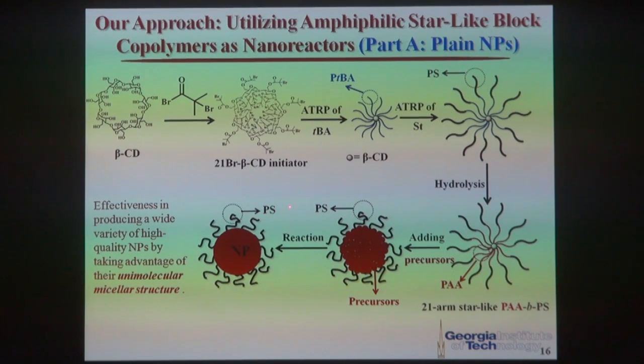So now because of the covalent connection between polystyrene and polyacrylic acid, right? They are covalently connected. So we are talking about nanoparticles with superior long-term stability. There is no dissociation and association of the surface ligand, in this case polymers, from the nanoparticle surface. So we are getting long-term stability for the resulting nanoparticles.